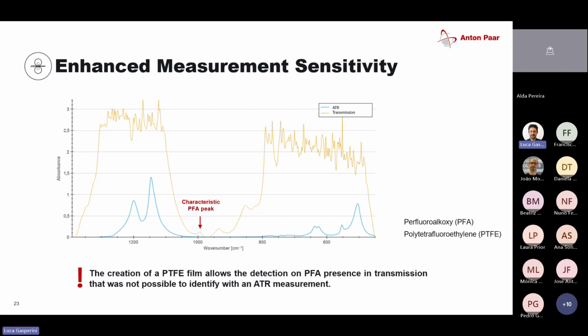You can see here, I cannot get any information out of this because all of these peaks are in saturation. It absorbs too much. But down here, I can see a tiny little peak, and this tiny little peak would not be visible on an ATR measurement. So if, for example, like we had this question with the sensitivity, you want to see trace amounts of an additive, like here the PFA peak, I can spot this only with transmission, because here I get a lot more response from the sample.